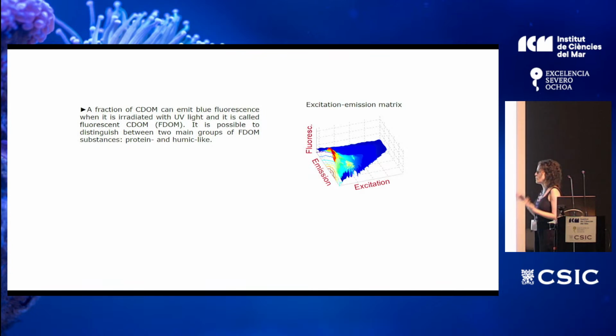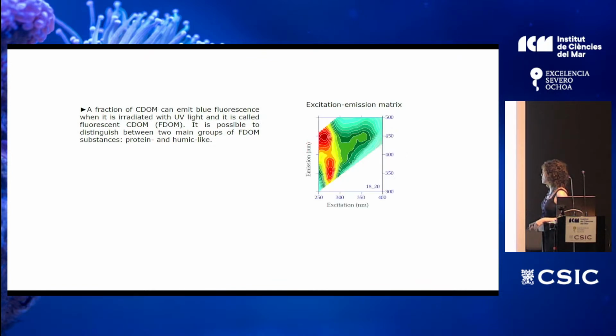So in the same way that we use it for the natural DOM in the water, in the ocean, we also use it to know more about the material released by plastic. To do that, we run a series of fluorescence spectra at different excitation wavelengths, but we recover them at the same emission range. And putting them one next to each other, we build this 3D matrix where we have excitation, emission, and the fluorescence here. And if we look at this from the top, we have something like this. The excitation, emission, and here the fluorescent intensity.